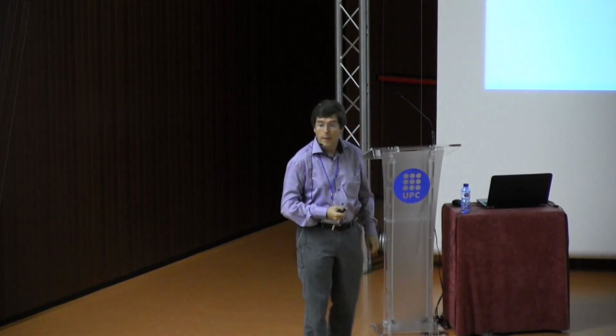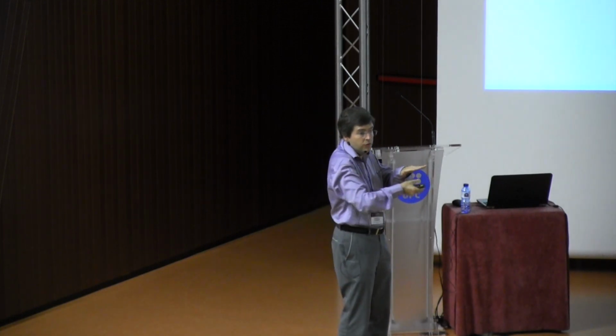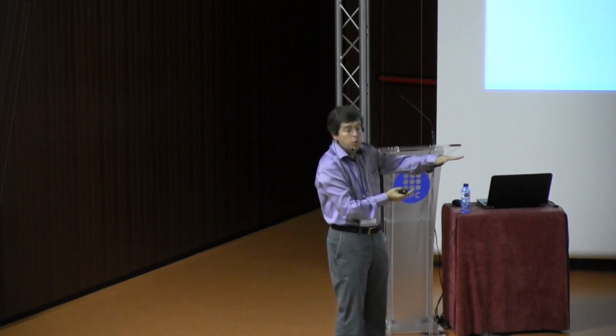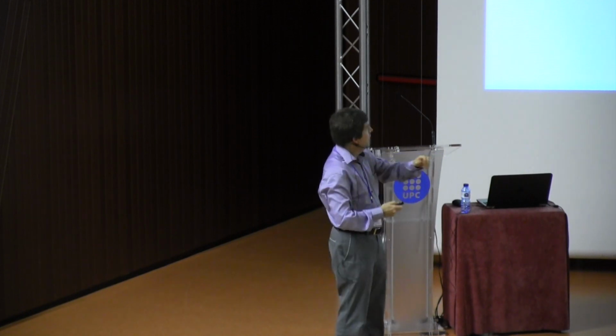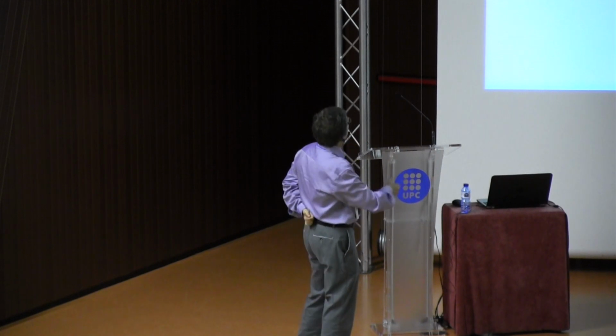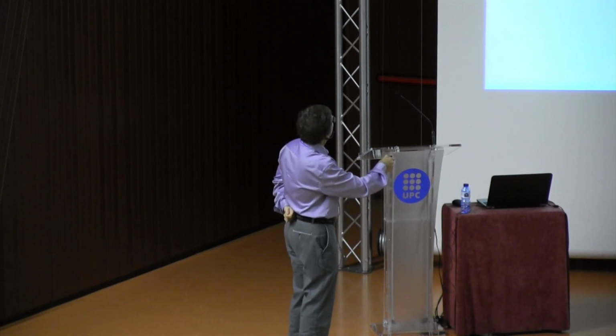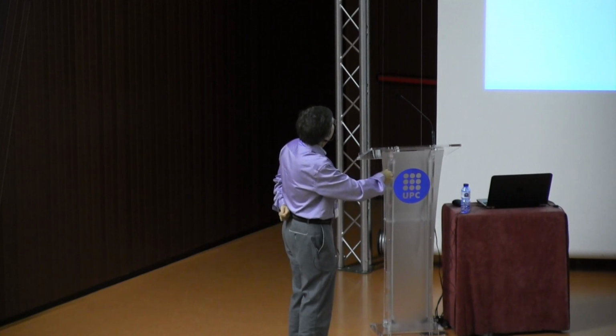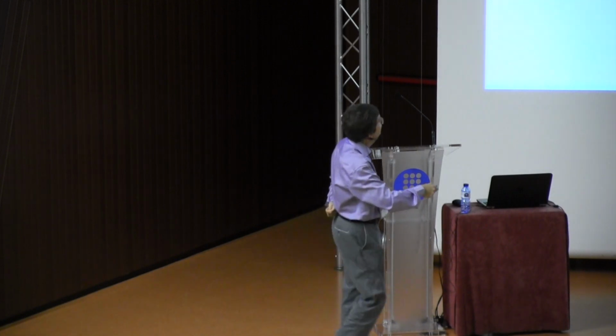Because if you do some shear of a metal strip in steel, you will have also propagation of Luders band. And you see in the image correlation analysis, you see that the bands start at the grips, and then they propagate and they invade here. And again, you see the front.